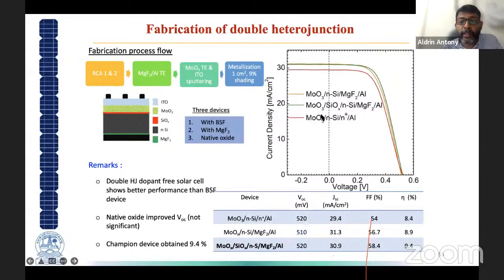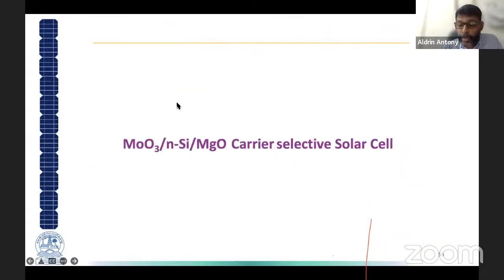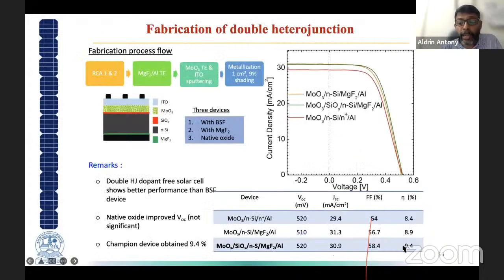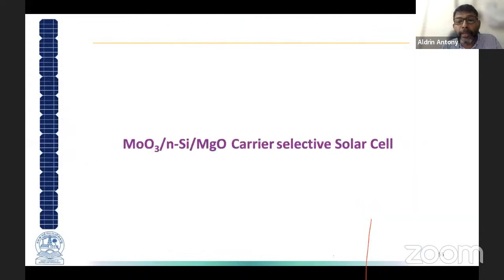You could see here, on one side you put MoO3 on the front side, and magnesium fluoride is put on the back side of a crystalline silicon solar cell. Both MoO3 and magnesium fluoride were thermally evaporated, and ITO was done by sputtering, and the efficiency was around 9.4%. So we further tried to find other new materials, and the other one was magnesium oxide.